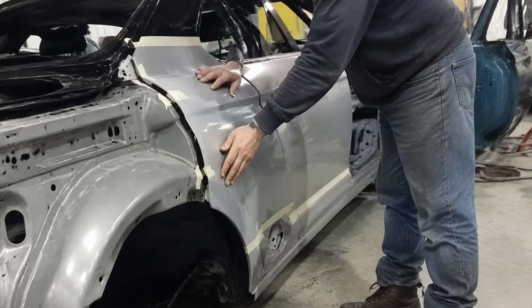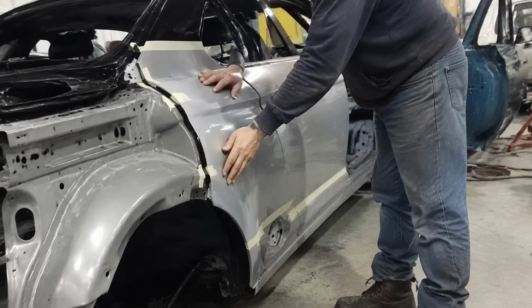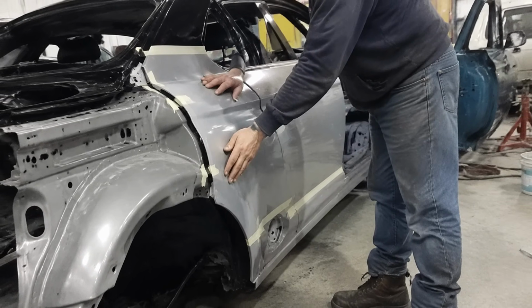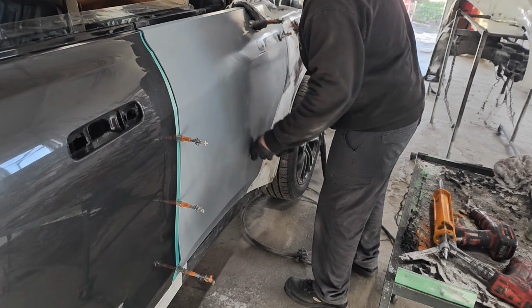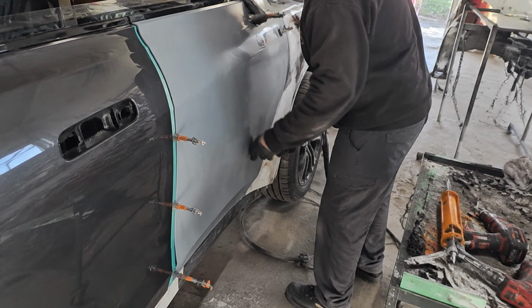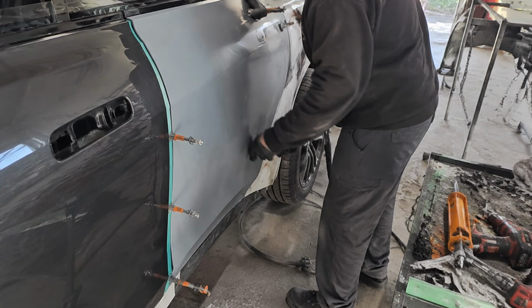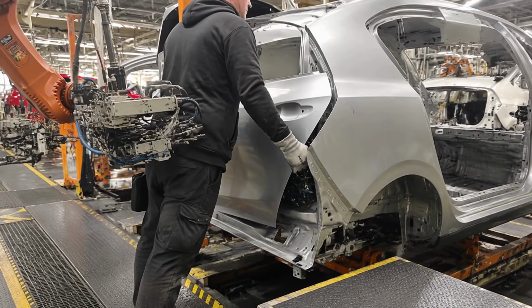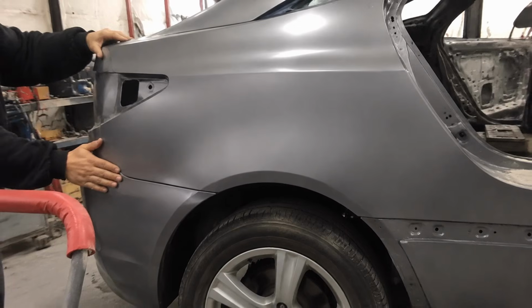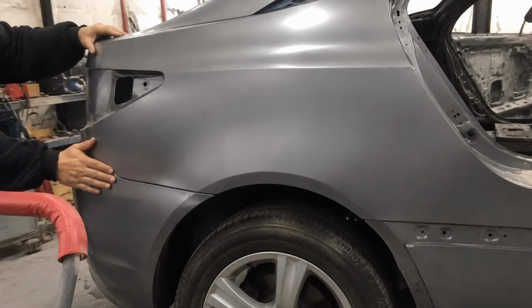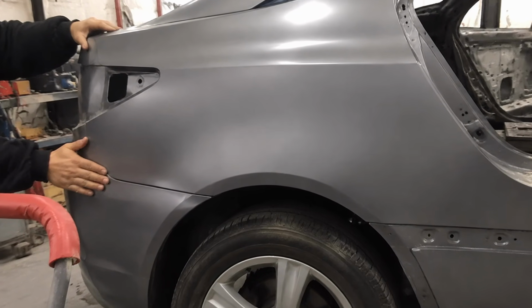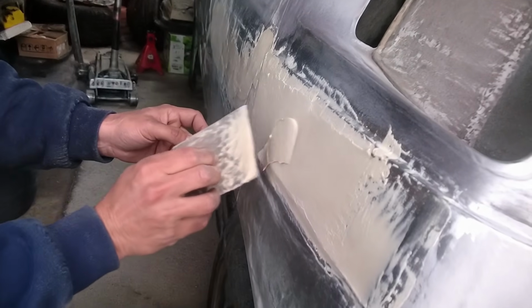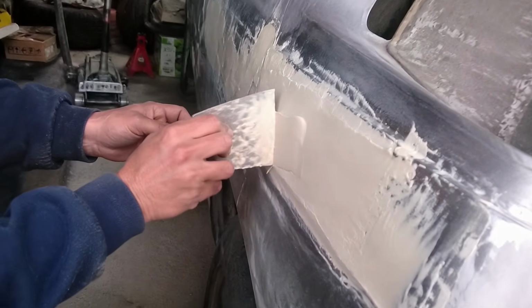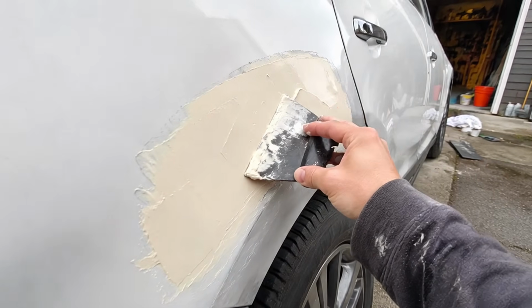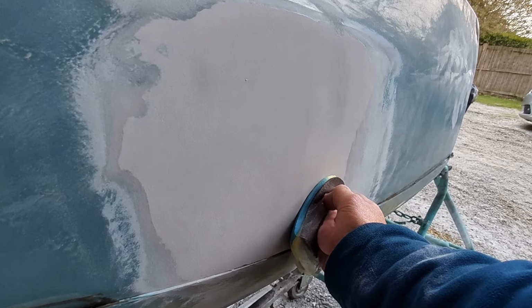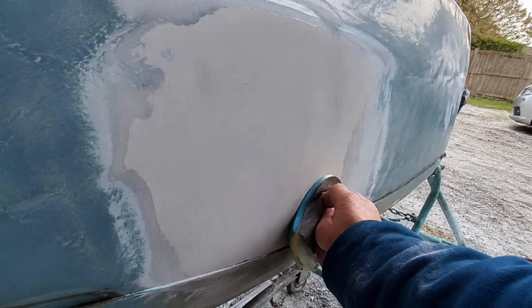That is as strong as, and in some ways stronger than, a spot weld. Because a weld is a series of little dots, and the adhesive grips the entire seam at once. This is not a backyard shortcut somebody made up on the internet. This is what real collision shops do every single day. Modern cars roll off the assembly line with panels glued on from the factory. A good body man will bond a whole quarter panel onto your car, and you would never know it wasn't welded. Once the hole is bridged, whichever way you chose, you shape it. You skim body filler over the patch to bring it flush and smooth, filling the low spots, feathering it out into the good paint.